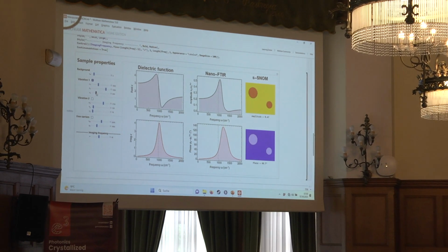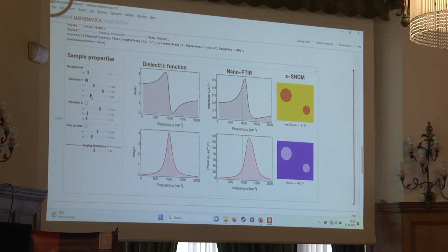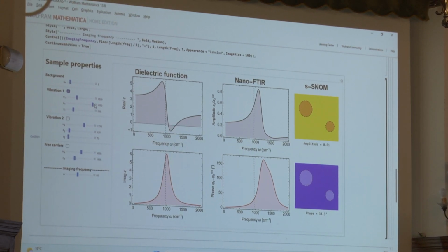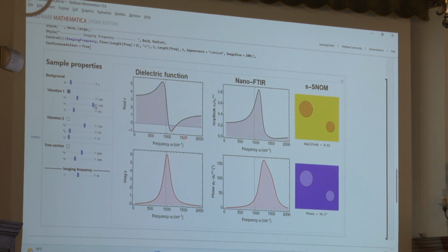Yeah, so now the permittivity is almost reaching 0. We can see already it's somehow asymmetric. So something is changing from the shape already. So we don't have this one-to-one correspondence anymore as before. But we can make it even stronger. And now we have the situation where the permittivity is -1. This was mentioned already many times this week. And what happens now is that the amplitude signal is getting really large. There's this resonant tip-sample coupling. There's a damping, so the absorption is quite high. I think I can make it a bit smaller.